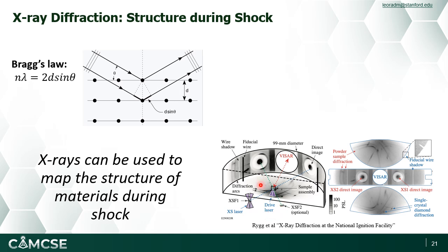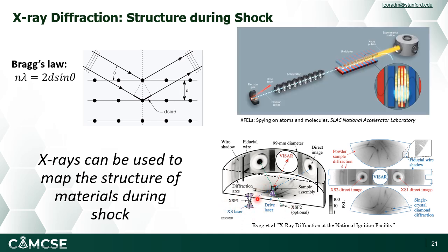At some of the largest laser facilities in the world, like the National Ignition Facility at Lawrence Livermore National Laboratories, we have a few different types of systems that allow for X-ray diffraction using a backlighter, which is effectively a way of simply shining a very powerful laser at a metal to generate a more broadband version of X-rays. And this allows us then to capture the diffraction patterns as arcs that look something like this.